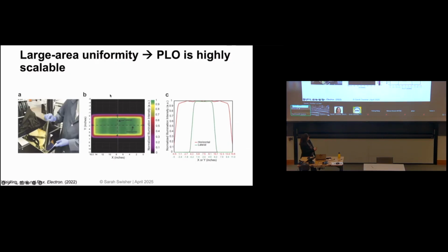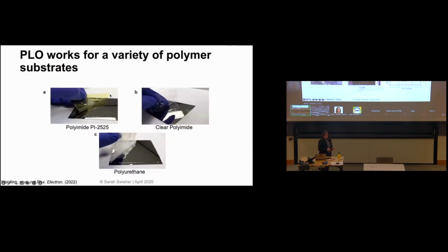And this is scalable because what you're seeing here is a large glass substrate. It looks like a mirror because it's coated with that light absorbing layer. So from this direction, the film is being peeled off of that glass substrate here. And you can see that this is scalable because we can essentially move the lamp and line up the flashes of this lamp and still get really, really nice uniformity. So that big green block is showing you that you've got about 90% uniformity across that processing area there.